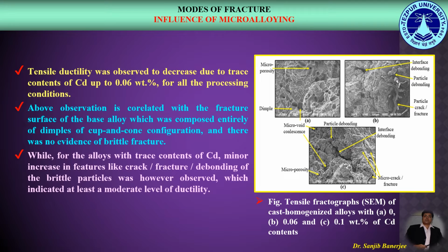Let us first study the influence of microalloying on the fracture surfaces of the investigated alloys. Here we can see the tensile fractographs of the cast homogenized alloys with 0, 0.06 and 0.1 weight% of cadmium. Now, the tensile ductility was observed to decrease due to trace contents of cadmium up to 0.06 weight percent. Such observation is correlated with the fracture surface of the base alloy, which is composed entirely of dimples of cup and cone configurations, as we can see in this figure, and there was no evidence of brittle fracture. While for the alloys with trace contents of cadmium, as we can see in figure B and C, a minor increase in features like crack, fracture, debonding of the brittle particles was however observed, which indicated at least a moderate level of ductility.